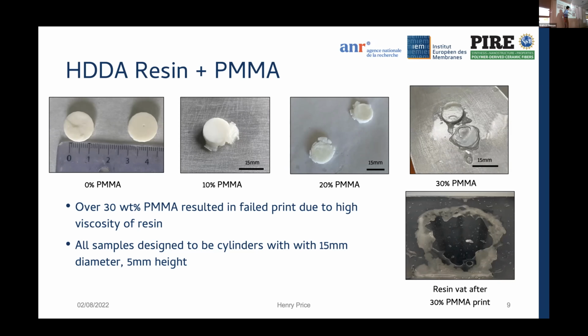You can see on this image on the bottom right, this is the resin vat after the print. All the resin is separated around the outside, and the printing area is in the center. That's because the viscosity was so high, it could not flow completely to cover the surface, and therefore could not provide enough resin to form a new build layer. Also, there are some edge definition issues with the PMMA, but those were alleviated by some slight restructuring of the printing parameters in the printer itself.